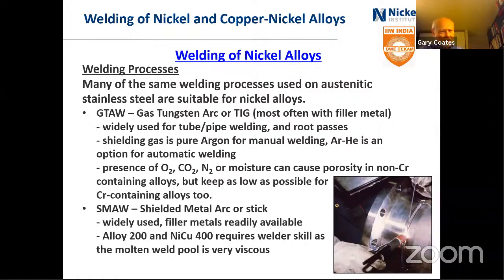Presence of oxygen, carbon dioxide, and nitrogen and moisture can cause porosity, especially in the non-chromium containing alloys. We'll come back to that in a minute when we look at the copper nickel alloys too, but keep it as low as possible for the chromium containing alloys. And if you see porosity in a weld, look for sources of oxygen or carbon dioxide or nitrogen or moisture in the welding process.